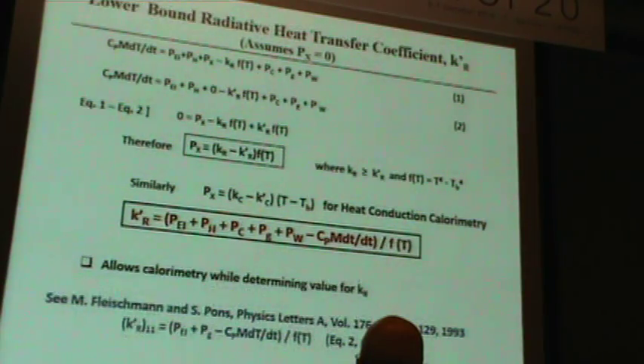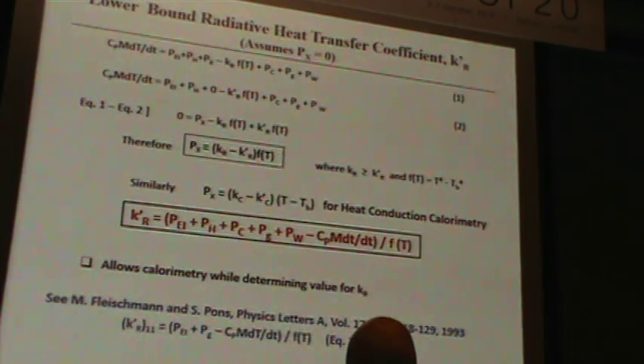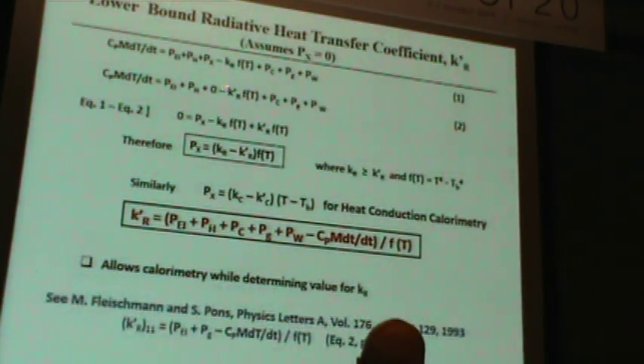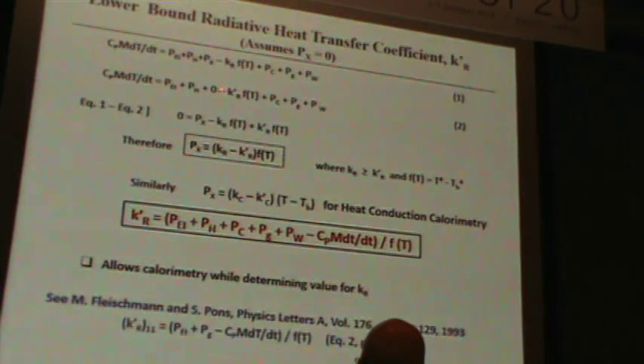The lower bound is what Fleischmann and Pons often use. This is an important paper. You can read all about it in this Physics Letters A paper. But they assume there's no excess heat. Here's the correct equation. You can assume the excess heat is 0, and then your constant has to change to compensate for that. It has to be less. If the power is less here, the constant has to be less here, the negative and the positive, both are less. So you get a simple equation which is very accurate.